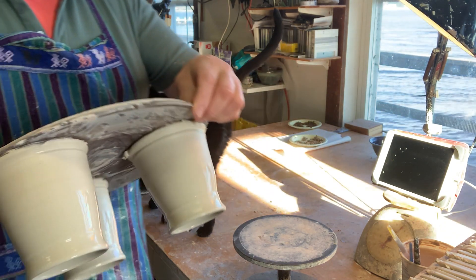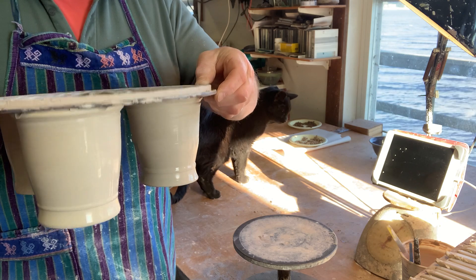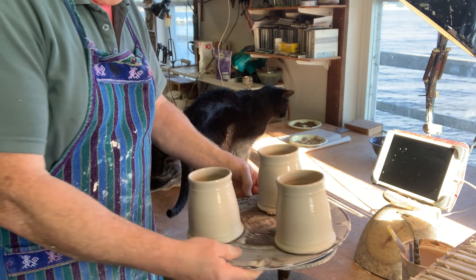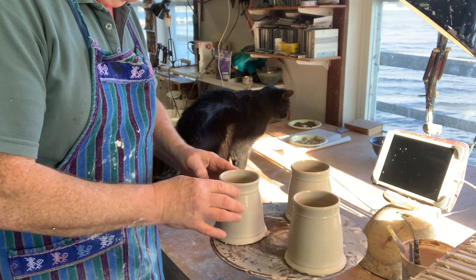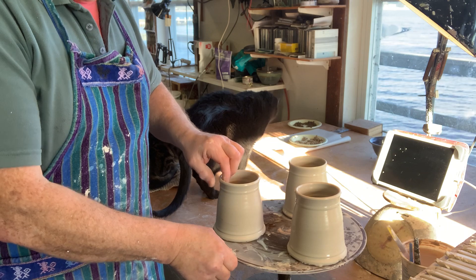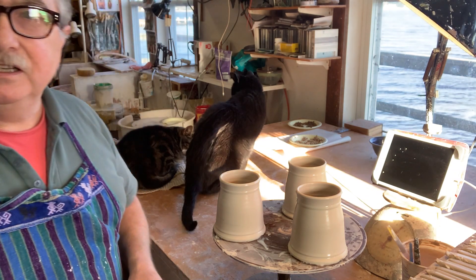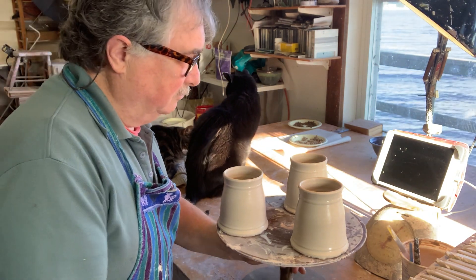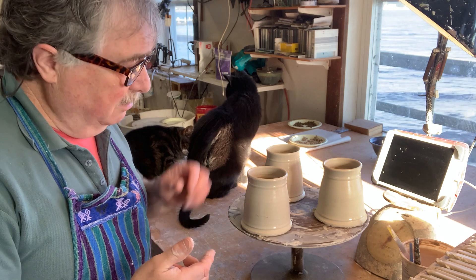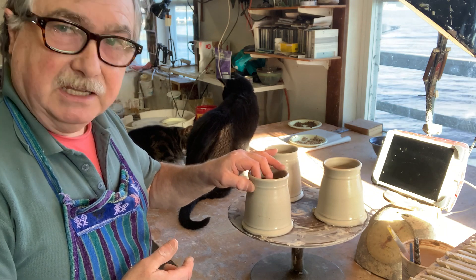These are from yesterday — I just dipped them upside down in a bucket of water to wet the tops again. I store my pots overnight in a damp cupboard so they don't dry out completely, and they're still a little bendable. You've got to make sure that when you put handles on, you can actually bend the pot fairly easily. I can spray them or just dip them upside down in water — see how easy that is to bend now, leaving a fingerprint in the surface of the clay.